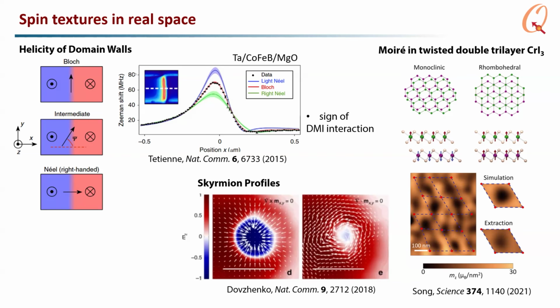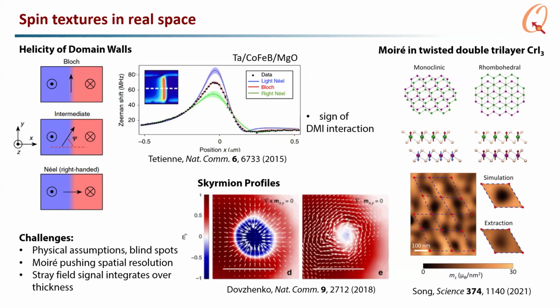Right. So triple Q. Our spatial resolution is about 50 nanometers, so I think triple Q might be too small. But you can also look at skyrmion profiles and also look at the Moiré pattern, the Moiré unit cell in twisted chromium iodide, where you see patches of ferromagnetic regions and patches of antiferromagnetic regions.